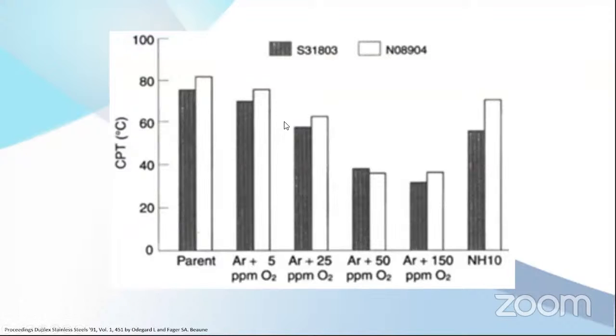And this is what happens to corrosion resistance when you have oxygen contamination. This is an example of the duplex and high alloy austenitic stainless steel. This is 2205 duplex. This is 904L. So the parent material has a very high critical pitting temperature. Critical pitting temperature is the temperature when pitting happens. So the higher the temperature is, the better the material.